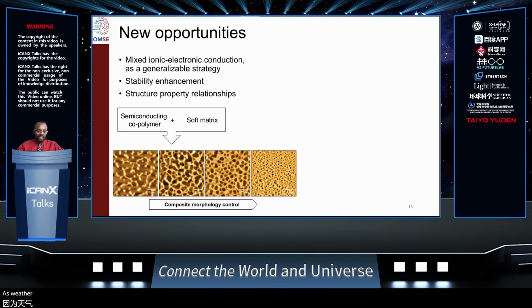So why is this important to us to design new materials? Because now, simply by copolymerization strategy, we have actually started opening up novel opportunities in terms of materials. For those of you who know me a little bit, you know that I like to mix things, and here I'm using one example to demonstrate what I mean by that. With this copolymerization strategy, we've been able to show that we can start to modulate its nanostructure simply by making composites. Here, if we take our DPP copolymer that I mentioned, we can mix it with a soft matrix, and we can control the nanostructure, the physical property of this material.